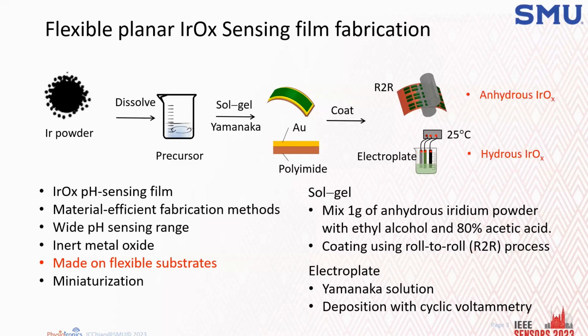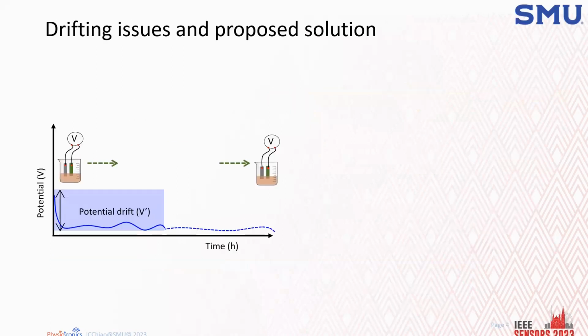One approach gives anhydrous iridium oxide, because the baking takes away most of the water molecules. The other one, electroplated, is hydrous oxide, because there are a lot of water molecules trapped inside the iridium oxide. So we do expect that there will be different responses to the drifting mechanism.